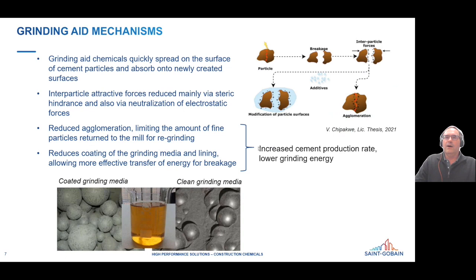What are the mechanisms by which the grinding aids work? It's pretty simple. These grinding aid chemicals simply adsorb onto the surface of the particles. Whereas when you break apart these particles, the surface forces want to bring them back together and have them agglomerate, the grinding aid chemical just adsorbs onto the surface and prevents that from happening. So there's some steric hindrance and it neutralizes the electrostatic forces and just basically acts as a dry dispersion.